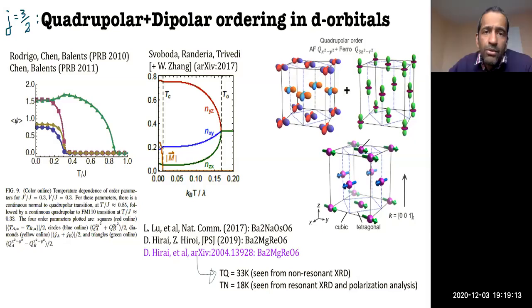Orbital ordering, you don't need inelastic X-ray, right? This is just X-ray diffraction to look for the orbital order. But if you're talking about the structure of levels, the excitations in the excitation spectrum that I was showing, then people can even do high energy neutron scattering. If these splittings are on the scale of even 100 millielectronvolts, you can come in with high energy neutrons and actually see excitations between these different orbitals, which people have done. So that's another possible probe.